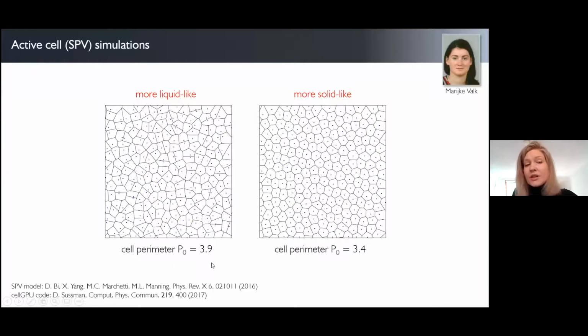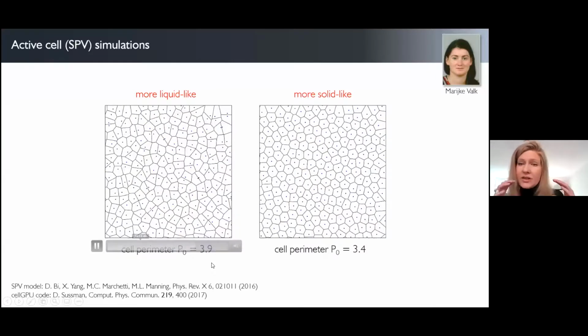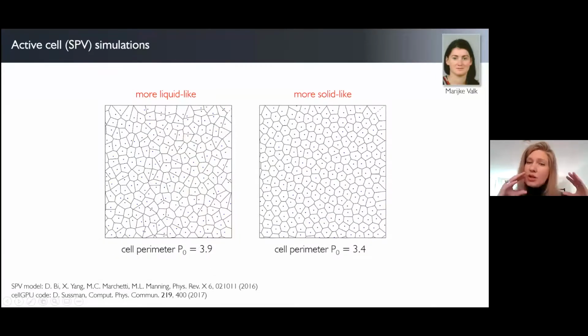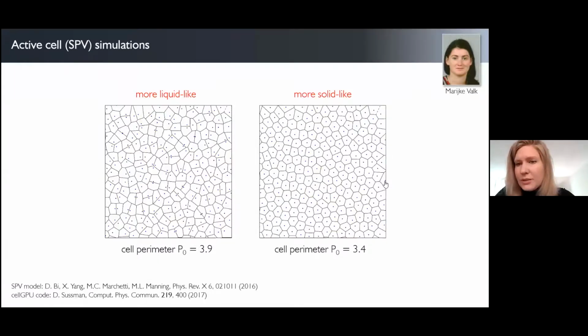And the only difference in these two videos is basically what is called the preferred cell perimeter. So basically how elongated these cells like to be. On the left, they like to be a bit more elongated, and on the right, they like to be a bit more circular. And that's enough to tune the dynamics from more liquid-like to more solid-like behavior. And then Marijke extracted static structure factors from all these simulations and the intermediate scattering functions to quantify the dynamics, and then applied a mode coupling analysis to these results.